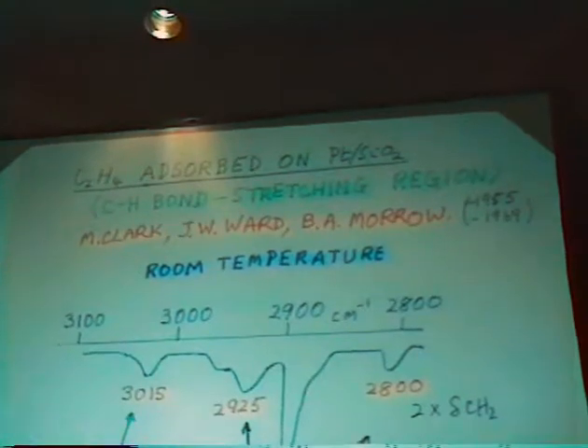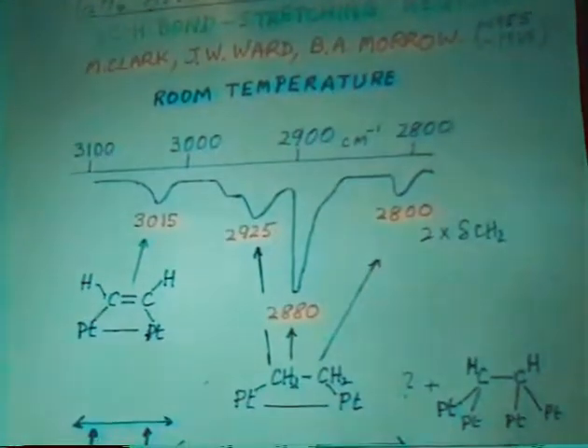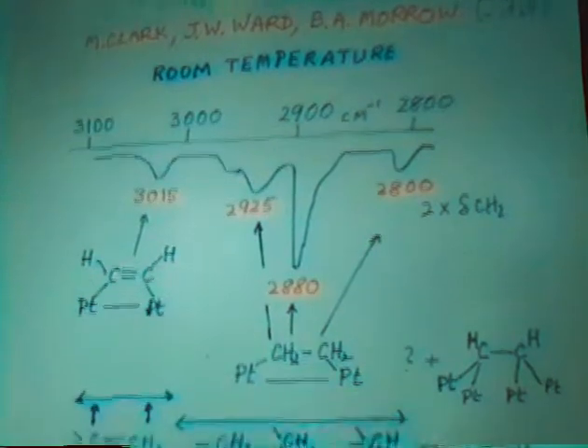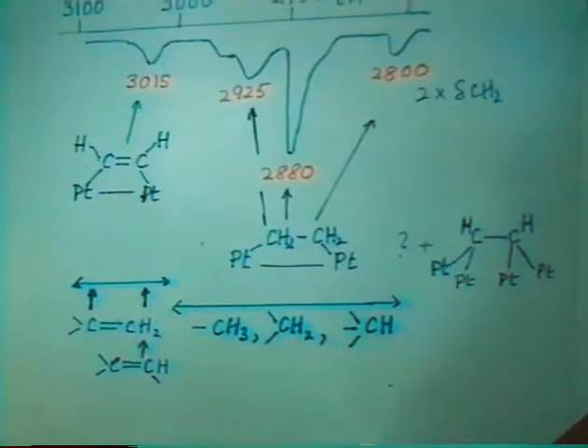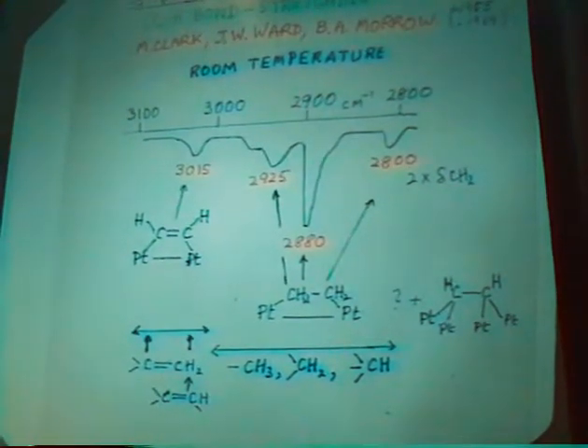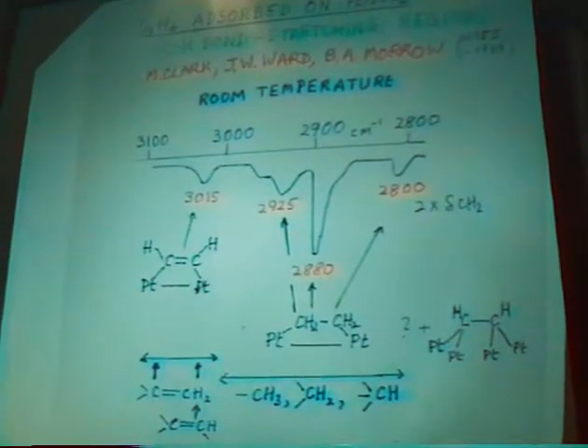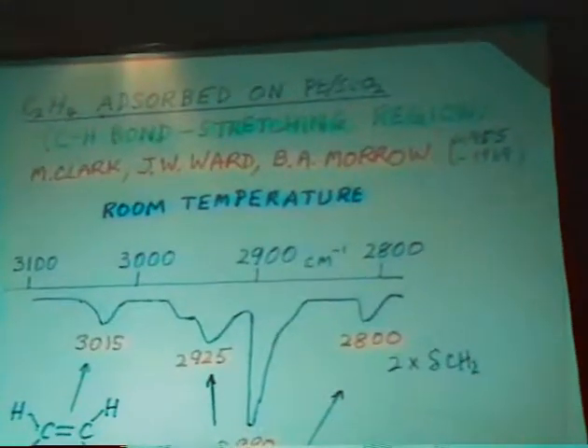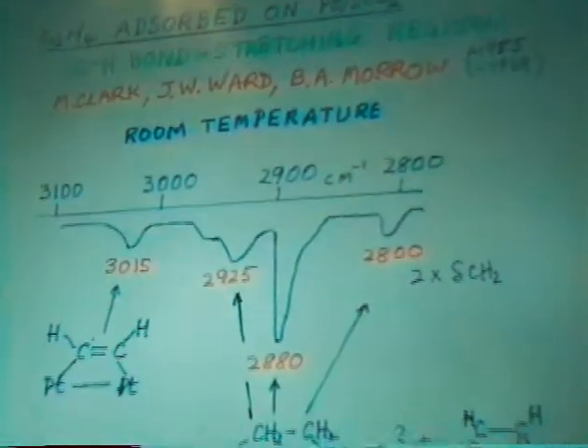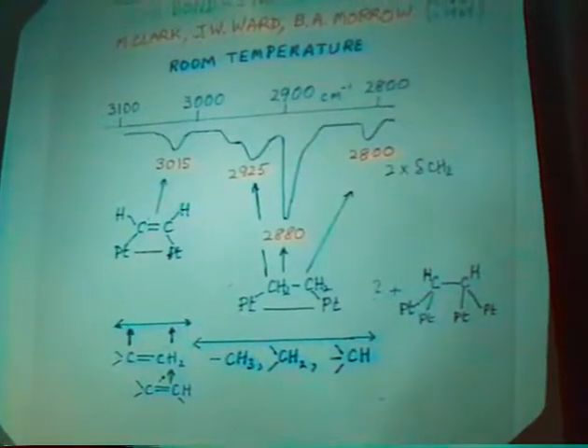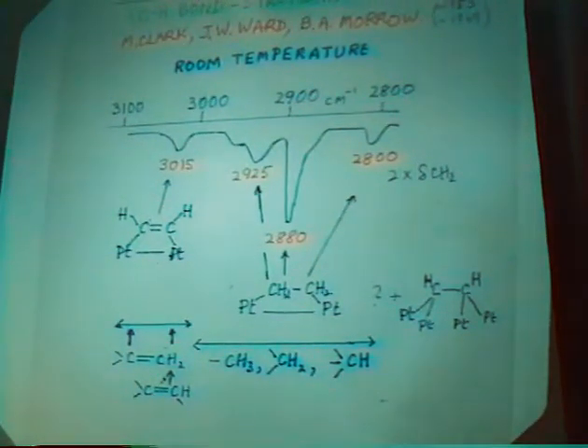And this was the spectrum that we finally published in the CH stretching region, where we have no interference from the silica background. And I'm going to tell you how we interpreted it, and why. Well, first of all, there were clearly bands above 3,000 wave numbers which could be reliably assigned to an ethylenic type, to some sort of C double bond C, CH species. And then there were stronger bands at lower wave numbers which were clearly from surface alkane groups.